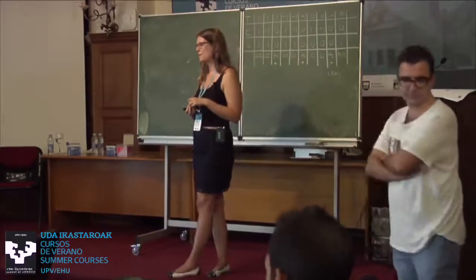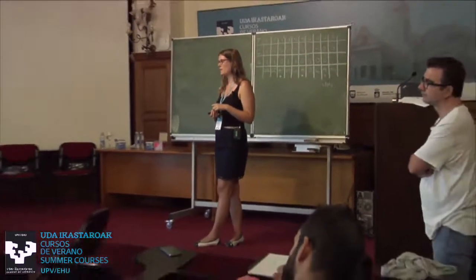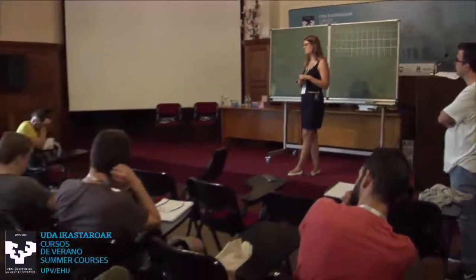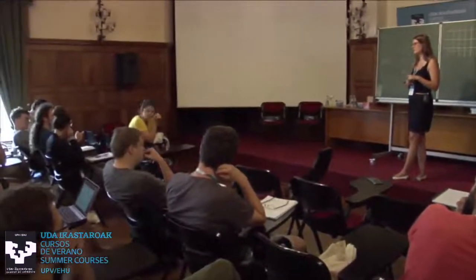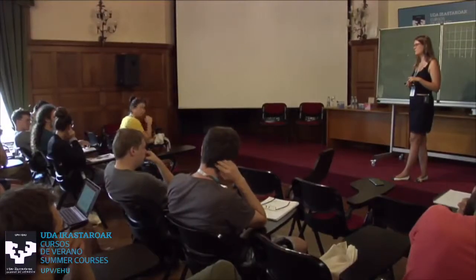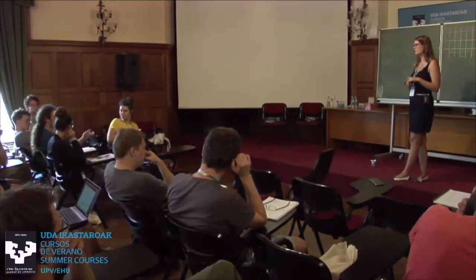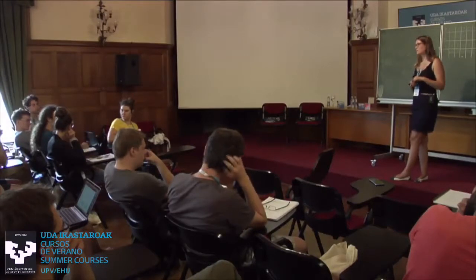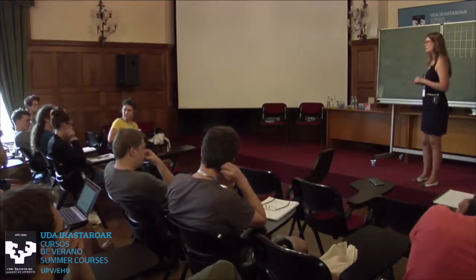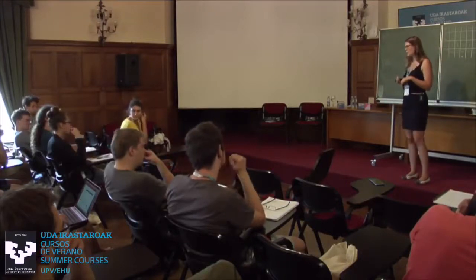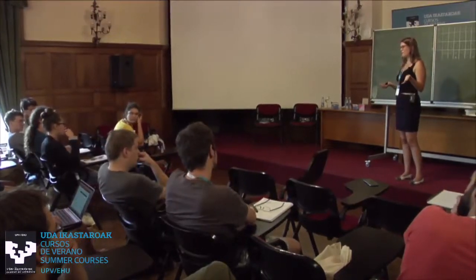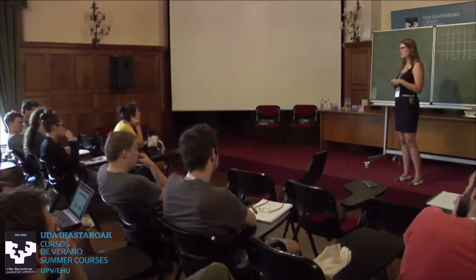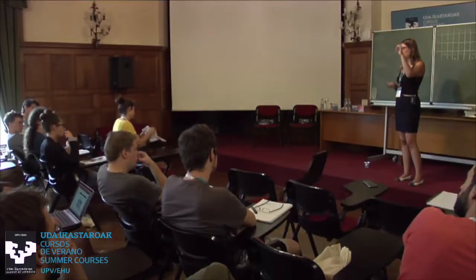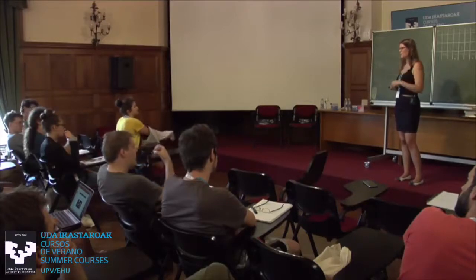You were talking mainly about 1-1-1 phases, and then switched to the large clusters that you showed at the end. But non-symmorphic crystal groups are most common. So what about other types of compounds? How does that come into play? Yes, you can also look for non-symmorphic 1-1-1 phases. However, then you will have the problem with the half-filled band a little bit. So actually, in my second lecture, I will talk about non-symmorphic 1-1-1 phases. And you will see that it will be really difficult to not have any pockets there to stabilize the non-symmorphic point at the Fermi level.